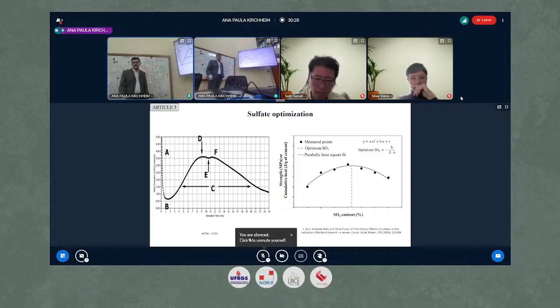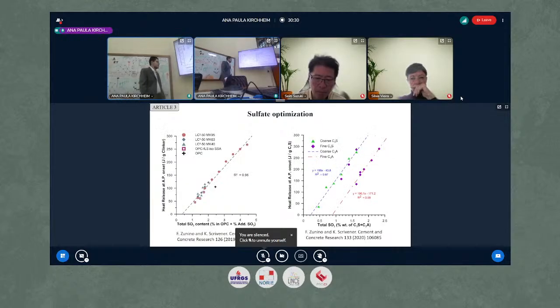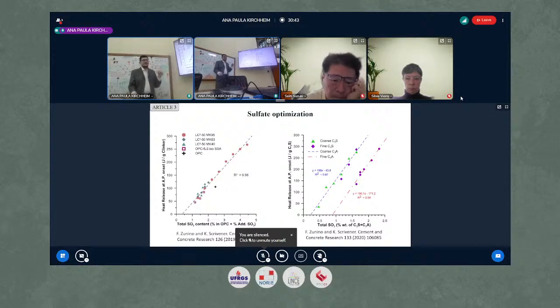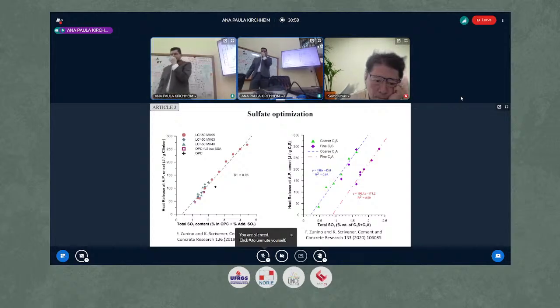But there are other ways. For instance, the one proposed is that we plot the heat release until the aluminate peak onset, meaning until the sulfate depletion point, against the total aluminate content, and we do a regression, and we analyze the intercept and also the slope of this regression, meaning if it needs more or less sulfate. I will explain this difference again later.